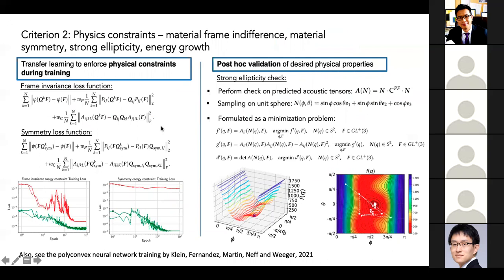also the physical constraint. So here we show 3 examples. If you're familiar with continuum mechanics, that should be pretty obvious. This is to train the large deformation constitutive law, a hyperelastic energy functional for HMX crystal. We can add a constraint there enforcing that if I rotate the observer, I should not change the energy, the stress, and the tangent predictions. And so Q is a rotation tensor that allows us to check whether, if I rotate the current configuration observer, I can get the same response from the mechanical principle. This can be incorporated into the training as well.